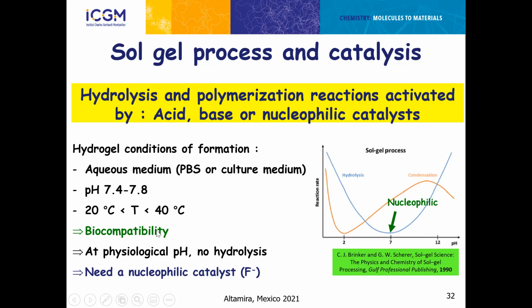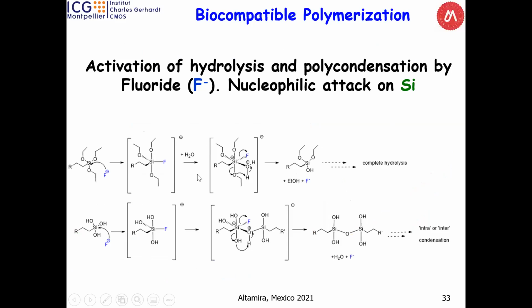If we are not under this biocompatibility, it's not possible to grow or to make some cell culture on the surface. So we started with F minus. Why F minus? You know, F minus is a more nucleophilic species, and the link is very suitable to coordinate on the silicon atom. Here I summarize why. F minus nucleophilic species can attack very easily this center, tetra-coordinated here, and you get a penta-coordinated center. And the penta-coordinated center is highly reactive by comparison to the tetra-coordinated one. And hexa-coordinated is more reactive than penta-coordinated, and so on.